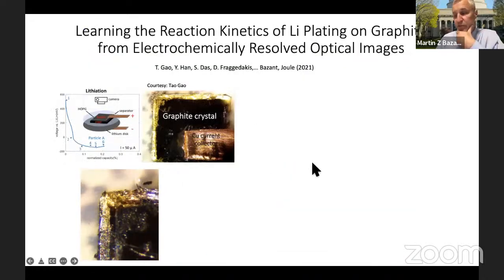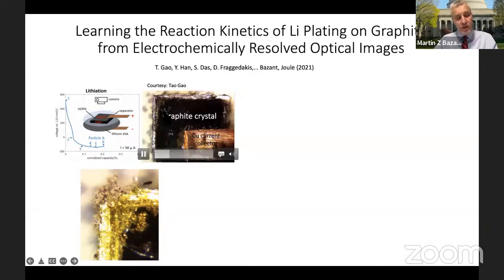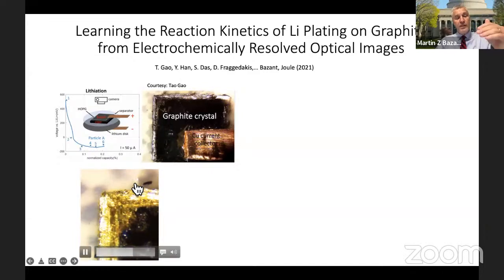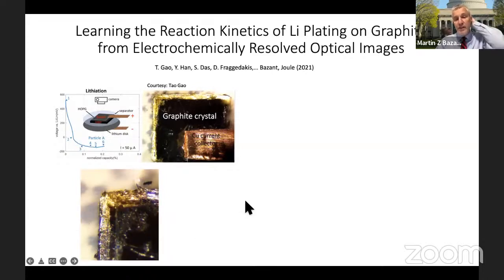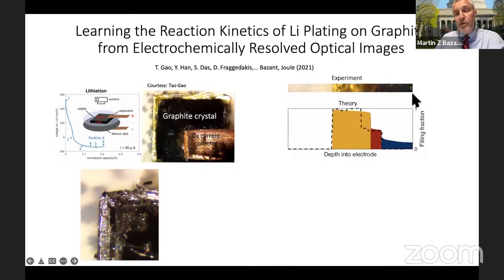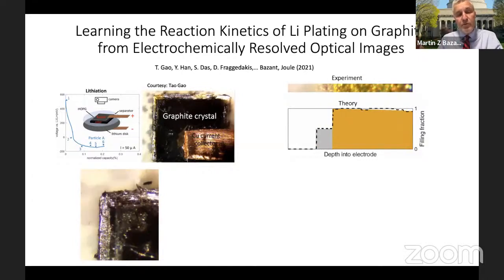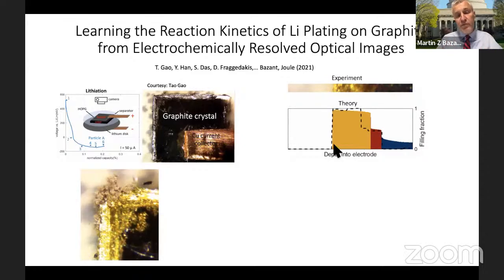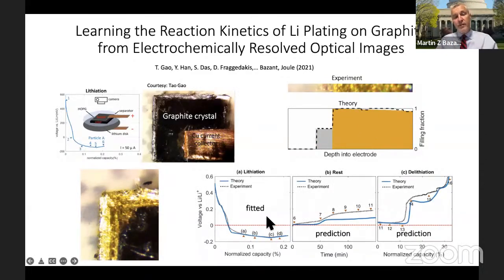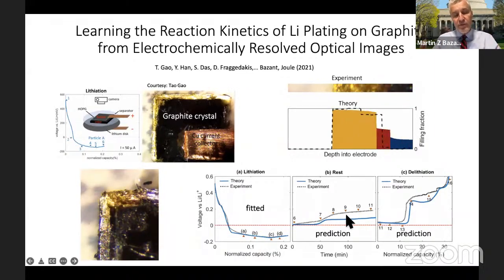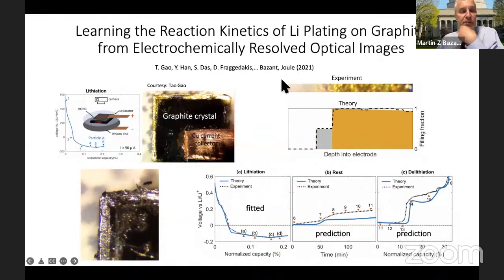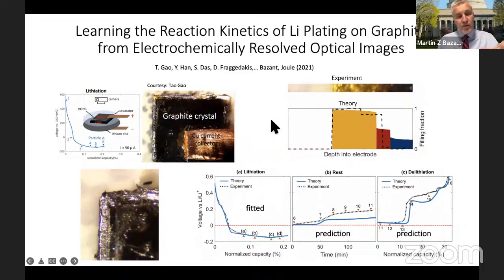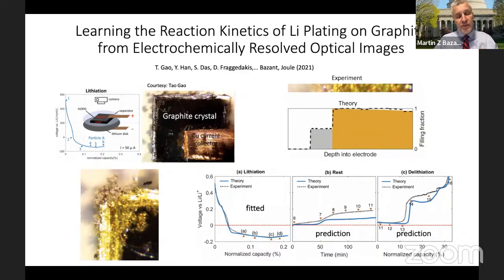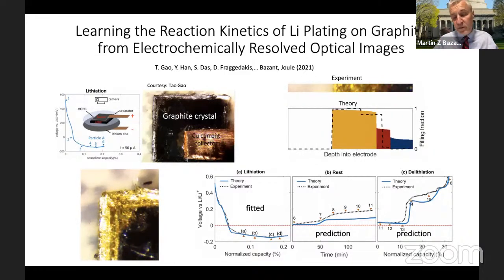Now, we have pursued the same strategy of image learning here as well. So these are some experiments from my lab where we actually took a large single crystal of graphite and observed the colors of lithium intercalating, and also observed how at high rates lithium metal can nucleate and grow on the surface of the graphite particle, as we see in the lower left. And again, we can digitize these images and compare with our models and have now an additional model for the lithium plating nucleation growth, which is learned from the images and also from the voltage data. And we're able to get a reasonably good fit of, let's say, lithiation, and then a prediction of what happens when the material's at rest, and also during delithiation. This was published last year. So I think here we're starting to get really deep insights using this image learning method into very complicated problems and important problems in electrochemical systems.